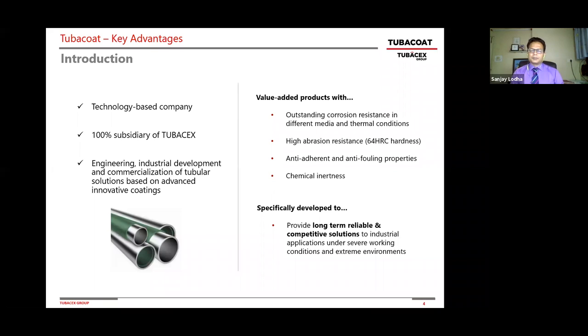The first step is called surface preparation. Whatever the substrate, it might be a new tube or an old tube that goes into a heater furnace, it goes through surface preparation, which includes sandblasting and chemical treatment, because the surface has to be very clean with the proper roughness to prepare for the coating. The second stage is an auto-controlled coating process that is applied on the surface through an automated process. Once that is done, it goes through an industrial-scale furnace where we vitrify it to bring about the chemical bonding between the substrate and the coating.